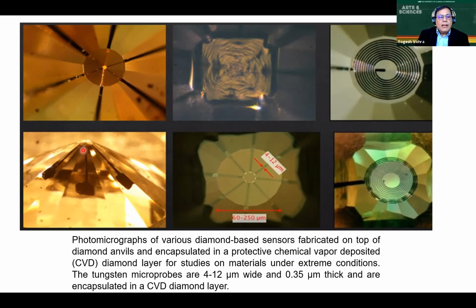So this is an example of the anvil in the bottom here, bottom left, and this is top left. You see this close up of these electrical probes, and the middle top here, you have a pattern which is encapsulated. After diamond growth, you see this rough area, rough steps due to the grown diamond. And then you can polish this off actually to expose your sensing probes. So here you see the metal, the shiny metal coming out are the probes which are sticking out of the diamond, and the rest of the probes are actually encapsulated in a single crystal diamond.